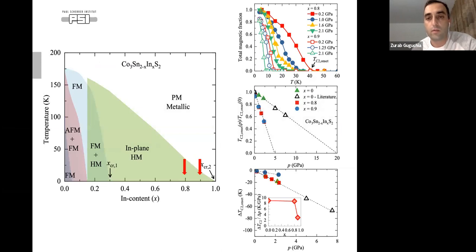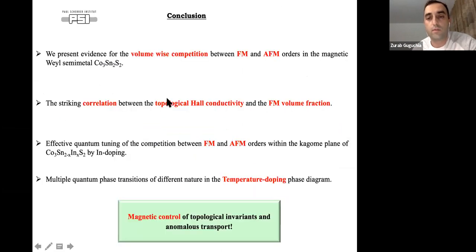Okay, so probably I will skip this. To conclude this first part of my talk, we show the evidence for the volume-wise competition between ferromagnetic and antiferromagnetic orders in this Weyl semimetal candidate. We saw a quantitative link between topological Hall conductivity and ferromagnetic volume fraction. We can very efficiently tune the competition between these two order parameters by indium doping, and then we find these rich multiple phase transitions in the temperature-doping phase diagram. And so we find a system where, through controlling the magnetic interaction, we can tune the topological transport.